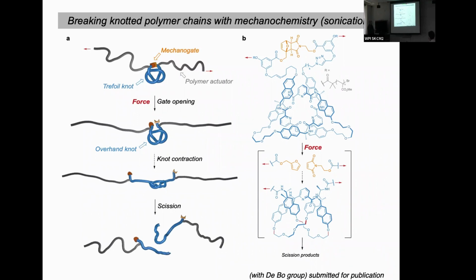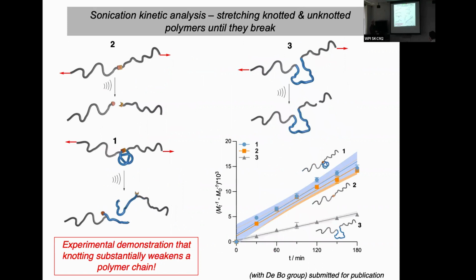So then we put this polymer into sonication, and when it's pulled, the first thing that breaks is the gate here. And once that's broken, then we've got a trefoil knot, but an open trefoil knot in the polymer chain that's being stressed by the sonication. So then the knot will be contracted by the pulling that goes on, and scission will occur. And we can see how easy that knot is to break, and also where it breaks. And these are the results.